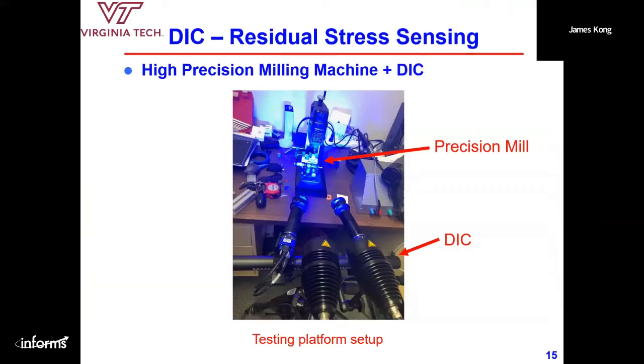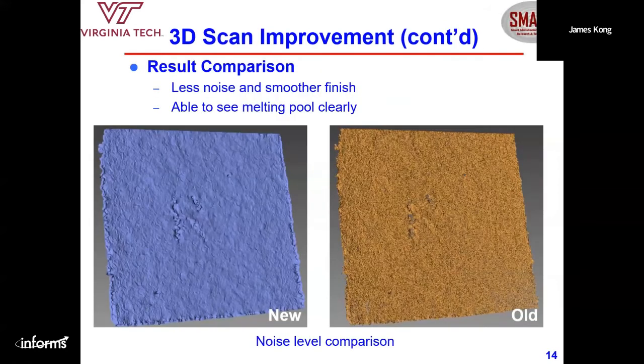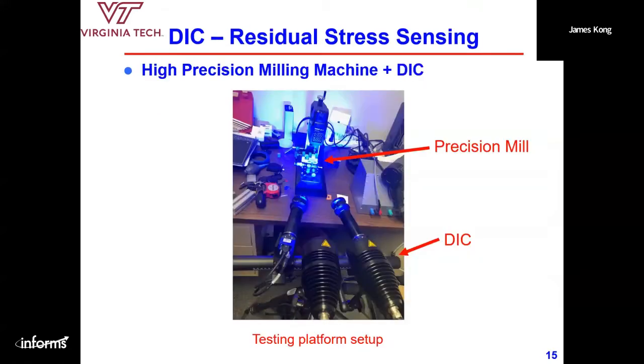This is another device called digital image correlation. It's still based on this kind of scanning technology. However, previously the scanning we saw is static. Whatever the part after the printing, we scan the surface to see the surface quality in terms of millions of data points. But this digital image correlation is dynamic, which means we can capture the surface dynamic change during the printing, for example, the residual stress and even the strain. Then we can correlate those measurements with the printing quality.